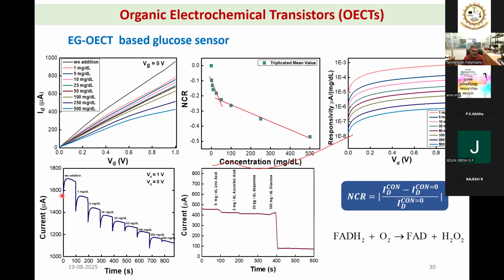And here also in the amperometric curve you are seeing a clear stepwise profile. In the previous case it was not, but here it is a clear stepwise profile for different concentrations. And once again, this is also not biased. It is simply the reaction happening on the non-biased gate electrode. And the interference study, once again, we have tested with dopamine, ascorbic acid, and uric acid, which are the predominant constituents in blood and the primary interferents of glucose. And obviously, these three are not interfering. Only when you add glucose, 100 milligram per deciliter, which is the normal physiological range, it gives a very sharp transformation here.